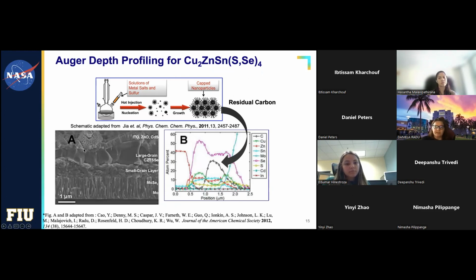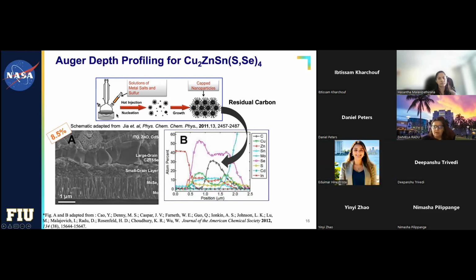I used to work for DuPont, and we created this very nice solar cell that had, in fact, an 8.5% efficiency, the one I'm showing here. But what we observed is that these nanoparticles are coming from the solution. They have some carbon on the surface, okay? So there is a lot of room for improvement when we work at the nanoscale, because in order to stop this thing from growing, you have to cap them. Once you cap them, you're going to have that carbon layer, these little rays that collect at the bottom here. Fortunately, they are conductive, so they are not going to impair the actual functioning, but they are certainly not going to give you a very good efficiency. And we did Auger profiling, and we see that this actually is carbon in here. So there is a lot of process to improve this, right?